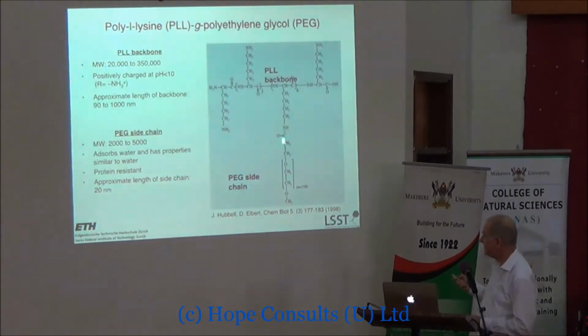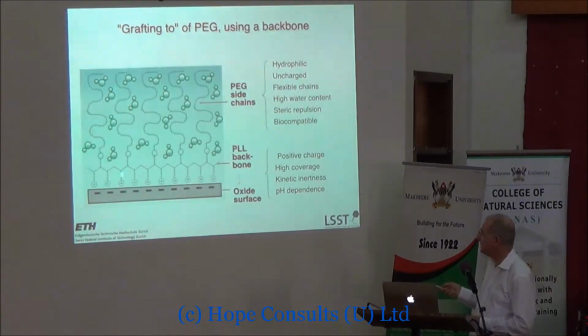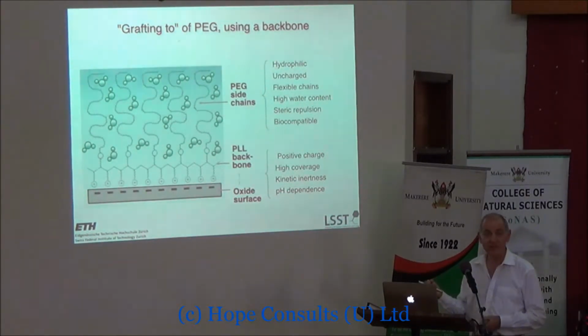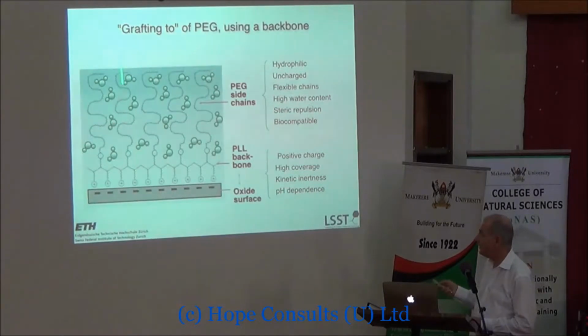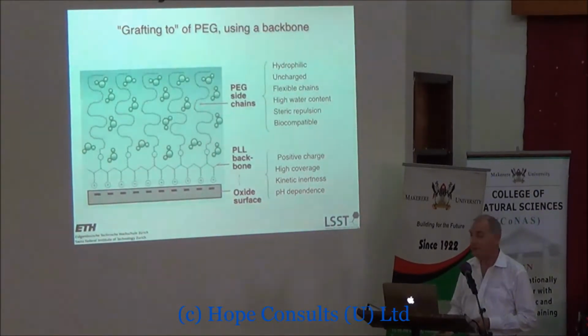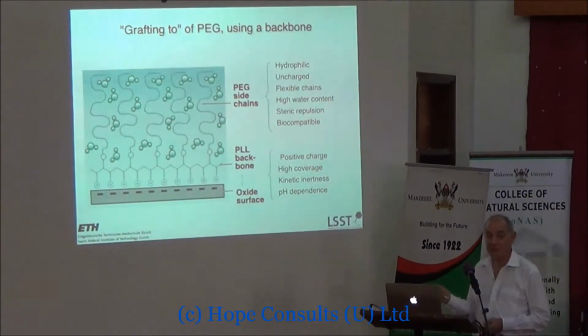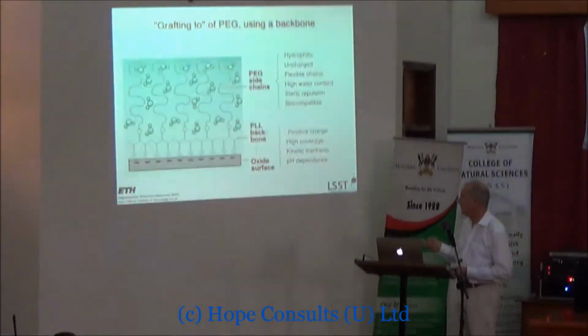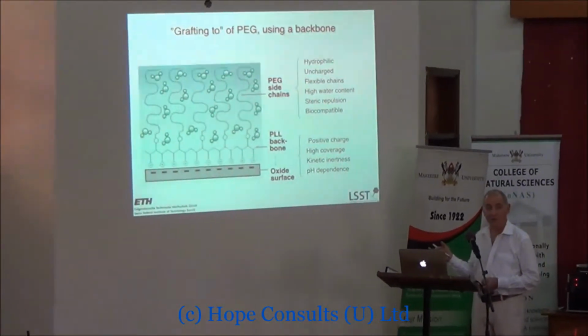But we can also use it to hook on side chains, so this is a long polyethylene glycol side chain. And in the end, it looks something like this. We have a backbone, we have the unused NH2s, which pick up their positive charge, and we have the side chains. These positive charges will stick on a negatively charged surface, and they'll force the side chains out into the good solvent, which in this case is water, so good solvent, polyethylene glycol. And just by dipping, for example, a silicon wafer into a solution of this polymer, which is commercially available now, you have a polymer brush on the surface.